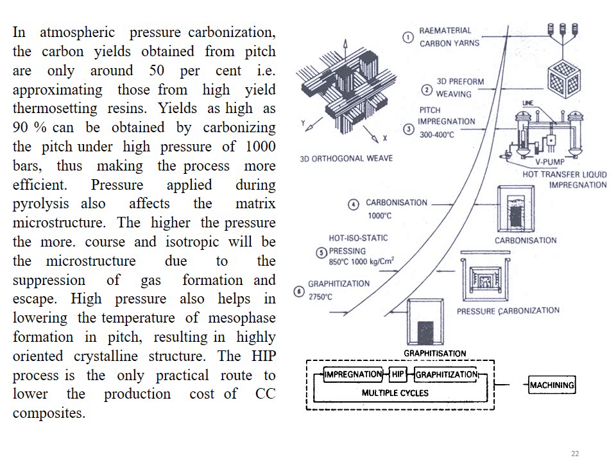The higher the pressure, the more coarse and isotropic will be the microstructure due to the suppression of the gas formation and escape. High pressure also helps in lowering the temperature of mesophase formation in pitch, resulting in highly oriented crystalline structure. The HIP process is the only practical route to lower the production cost of carbon-carbon composites.